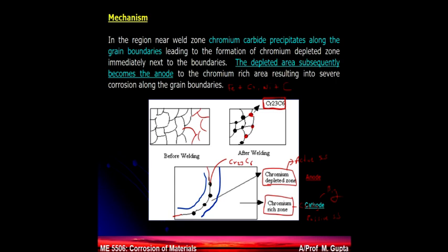The second option, if you look at the slide, 2 slides beyond that, I can put some elements like titanium or columbium in there, which will make carbides. So they will react with carbon and not chromium based on thermodynamics. So if the chromium is in the solution, it is the one which gives me the chromium oxide layer, and hence again you can avoid the intergranular corrosion.